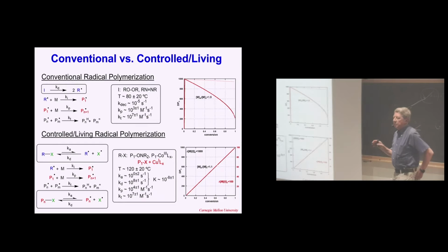So what is the difference between conventional and controlled radical polymerization? Intermediates are essentially the same. You have these free radicals. And if you look at these three reactions, initiation, propagation, termination, they are essentially the same here and there. The only difference is that here you generate these radicals irreversibly and very slowly. So the half-life of a radical initiator is approximately 10 hours. And here you generate radicals reversibly at both the initiation stage and also at propagation. And this makes a dramatic difference.